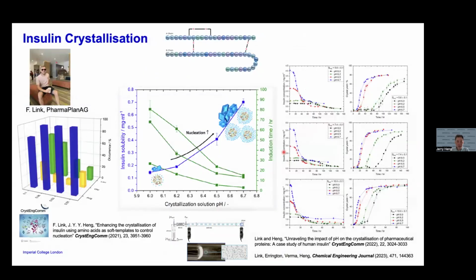Fredrik Link, who is now in consulting in Switzerland, worked on insulin, and in the case of insulin, we wanted to try to control its nucleation behavior using what we call soft templates. So these are the use of amino acids in solution. They are dissolved in the solvent, just testing on arginine, glycine, leucine. So the higher the bar, for example, the higher the green bar, demonstrates that with increasing amounts of leucine, the probability of the occurrence of insulin crystallizing out of solution also increased.